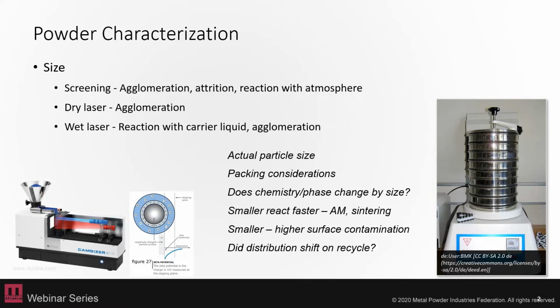And does your chemistry and your phases change by your size distribution? That's definitely been seen, and we'll talk a little bit more about those features. Again, smaller particles are going to react faster for AM and sintering applications, which can give you a higher density, but also additional hazards because of your higher surface area, so they can be more combustible and more flammable. And you can also get higher surface contamination. And did your distribution shift on recycling, which Amy already talked about.